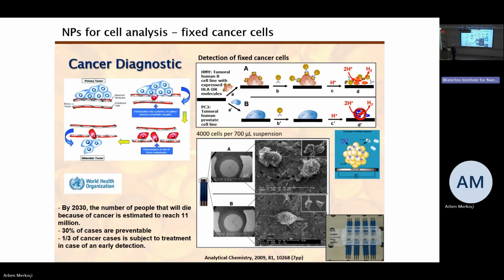So we took advantage of the hydrogen evolution reaction. Probably you know that this reaction is very much promoted by the presence of nanoparticles, gold nanoparticles. So we are able to measure the hydrogen evolution reaction and correlate this with the presence or absence of cancer cells. The more hydrogen evolution we have, the more cancer cells we have. So it is a kind of measuring the quantity of these cancer cells, their presence, for example, onto these electrodes, with interest for some clinical studies.